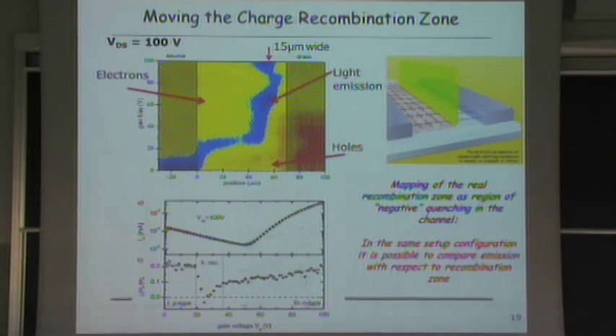Here, I show the result on the NT4N. These results are unpublished, so I cannot go deep in details, but it's clear to see that we can map the real recombination zone as a region of negative quenching in the channel. So in the same setup configuration, you can compare the emission with respect to the recombination zone.